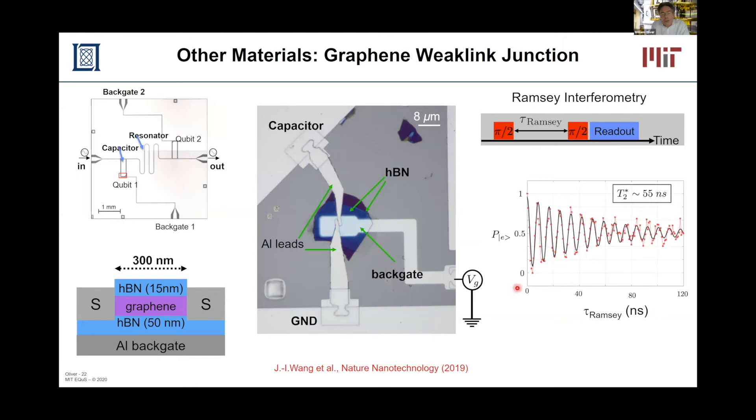This is an example of materials analysis on top of fabrication engineering. What are the fab processes that I can use to make high Q materials or high Q qubits or resonators. And so we've introduced deliberately a fabrication change to one region and observed its impact on the loss factor. The metal air increased by about 60%. We also see a small increase in the metal to substrate interface. But I think that this is within the error bars. So we do this regularly on all of our fabrication processes to understand how they're impacting on the qubit performance. We also make qubits out of other materials that might be considered nanoscience or nanotechnology. One is we made a qubit using a graphene weak link. We had a coherence time around 50 nanoseconds, which is good for a first try, but of course factor 1000 less than what we're getting with conventional materials.